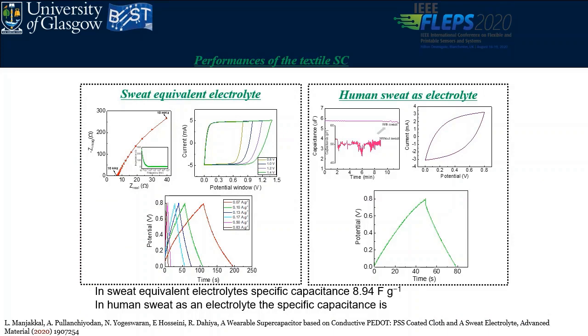Here you can see the difference in performance of the textile supercapacitor in a sweat-equivalent electrolyte and in human sweat as an electrolyte. In the sweat-equivalent electrolyte, you can see the impedance Nyquist plot showing how the resistance value varies, and also the cyclic voltammetric analysis with different operating voltages. In wearable sensors, the majority of electronic components require 1 to 1.5 volts for operation. So I carried out the studies up to 1.4 volts. The reason is that in sweat, water is the major component.